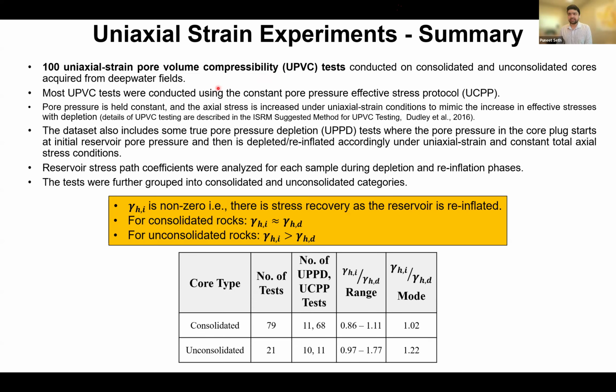There are two kinds of tests that were done. The first one is a UPVC, also you can say it's a constant pore pressure effective stress protocol. What happens in this one is the pore pressure is held constant and the axial stress is increased under a uniaxial strain condition to mimic the increase in effective stresses during depletion. The second type of test is a true pore pressure depletion test, in which the pore pressure of the core plug is actually depleted and then brought back to the original condition.